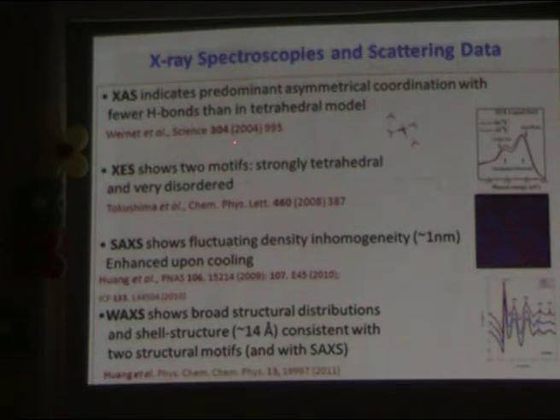Now, from X-ray absorption spectroscopy, we concluded back in 2004 that most molecules are actually not tetrahedrally coordinated or hydrogen bonded in liquid water, but instead have a broken hydrogen bond on one side. So we will be very sensitive to donated hydrogen bonds, but insensitive to what happens on the back of the molecule in accepted hydrogen bonds.